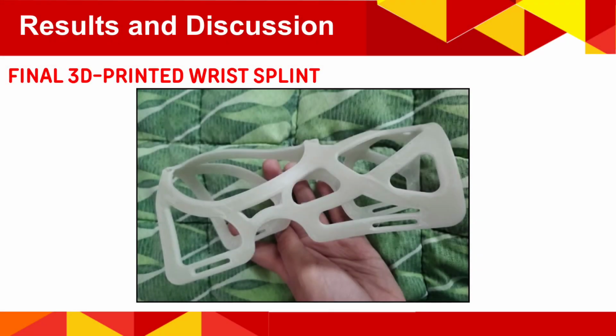Displayed on the screen is our final 3D printed wrist splint, which was designed specifically for carpal tunnel syndrome to provide both structural support and comfort. The design was sourced from Thingiverse, selected for its ergonomic fit and neutral wrist positioning, which is crucial in reducing strain and inflammation. To enhance its mechanical performance, we optimized the printing settings using Super Slicer. A rectilinear infill pattern was applied to the top and bottom layers to ensure a smooth and durable surface, while the middle section used a 25% gyroid infill pattern.